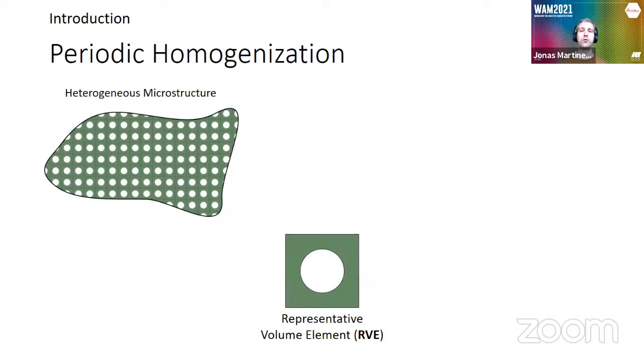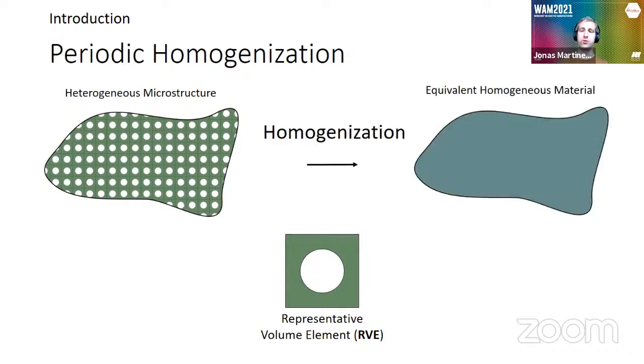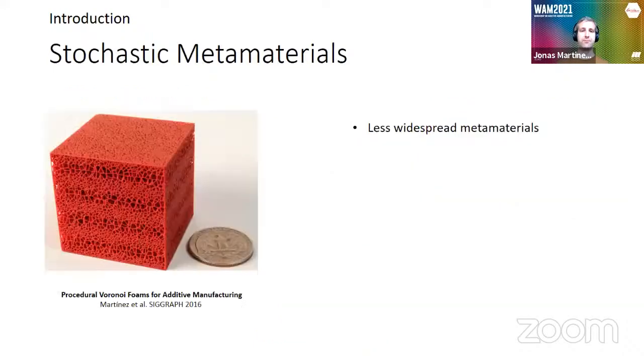So the common tool used by all these approaches usually is to consider homogenization, more precisely periodic homogenization. Periodic homogenization allows us, given a representative volume element that is periodically repeated, to extract the homogeneous material behavior, considering that this representative volume element size tends towards 0. So here the assumption is that we have something that is very, very small. And then we basically obtain the average behavior.